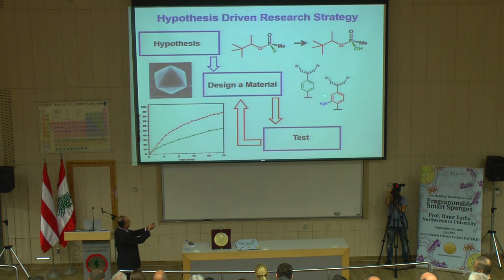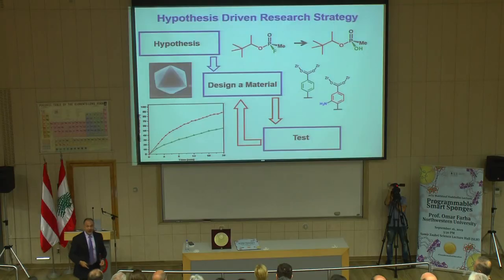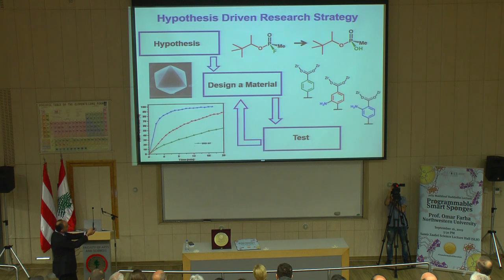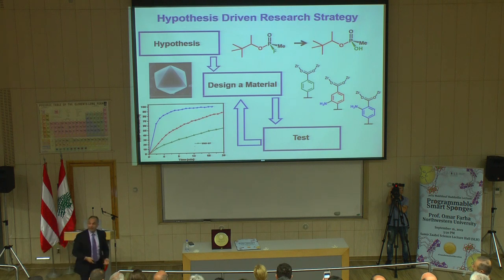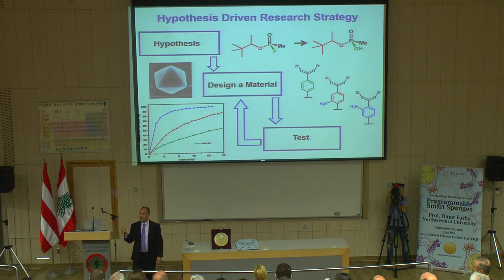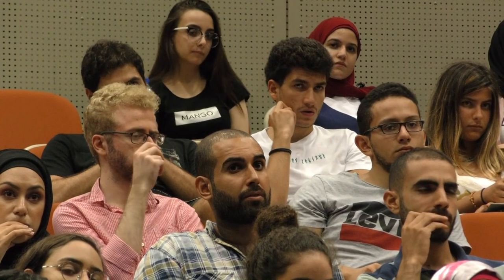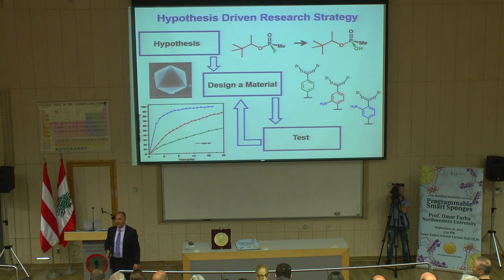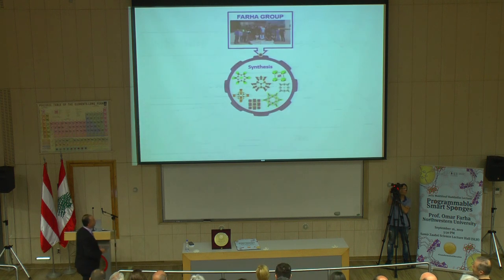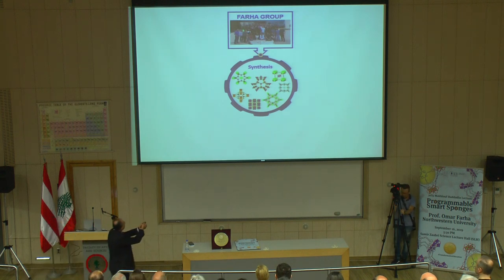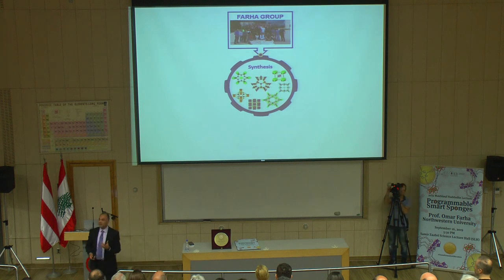We learned from enzymes that having a base in close proximity makes the catalysis better, and you could see it gets better. And now, if you just change the location of this amine from the meta to the para, you get a generation three catalyst that is that much better than generation one. Why am I saying that? Because if you have an amorphous material, that means you don't know the crystal structure, how can you even go about moving the functional group by two angstroms, which changes the efficiency of that catalyst? The only way you could do that is really knowing what the crystal structure is. In our group, we are a synthetic group at heart. So that's the core of our group.